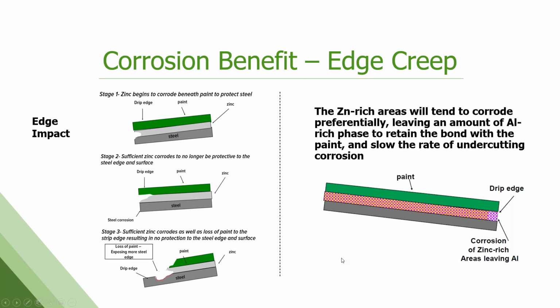Same thing on the edge. Again, my attempts at some artwork here. So you have a cut edge, a little bit of exposure there. On a galvanized product, that zinc is going to start to sacrifice itself and go away. Eventually, there's nothing here. Now you've got a flap of paint here. It kind of blows in the breeze and can peel up. And then eventually you get down to red rust, and you'll get red rust creepage up the panel as that continues to deteriorate. But on the edge of the aluminum zinc or the Galvalume panel, you're left with the aluminum framework there at the edge that greatly retards that edge creep that we see.